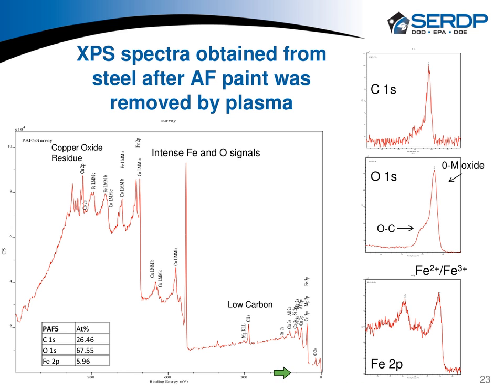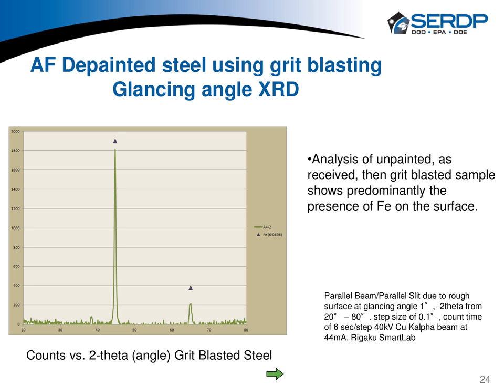Let's see. We used another technique which probes a little bit deeper into the surface, X-rays, which could be on the order of closer to half a micron or so in depth of penetration. If you're familiar with how they work, we used a technique called glancing angle because we were interested in the oxide or the very uppermost surface that we could get to. This particular sample was the grit blasted sample, and it was primarily iron with really very little trace of oxide on it. Now, if the oxide were on the order of 50 angstroms, like we saw in XPS, it might not be possible to detect that in X-ray diffraction.